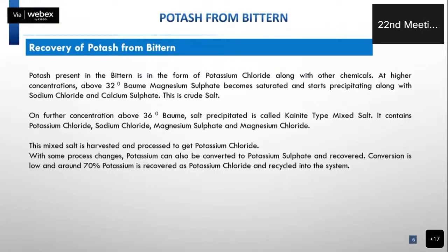The potassium chloride starts precipitating at very high concentration, at around 36 Baumé, where it becomes saturated and starts crystallizing. So we have to concentrate the bittern from 29 Baumé to 36 Baumé, and it comes out along with sodium chloride, magnesium sulfate, and a small quantity of magnesium chloride. So basically it is called mixed salt, and it contains potassium chloride, sodium chloride, magnesium sulfate, and magnesium chloride.